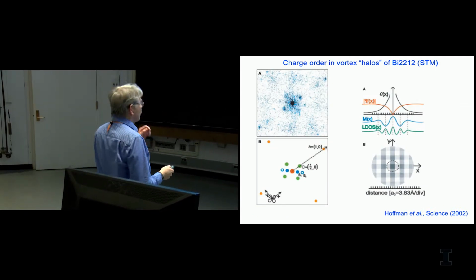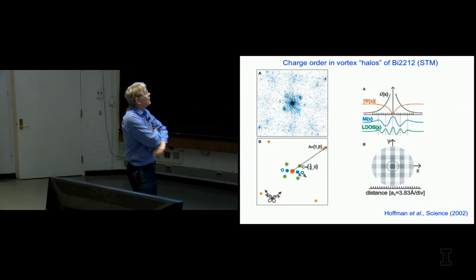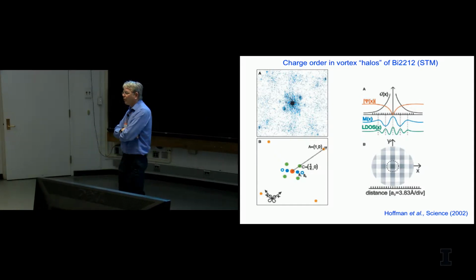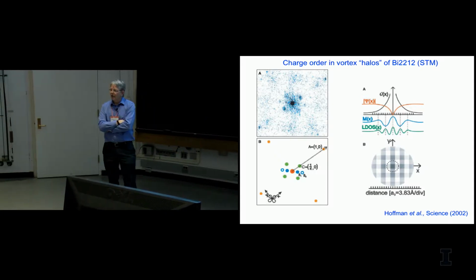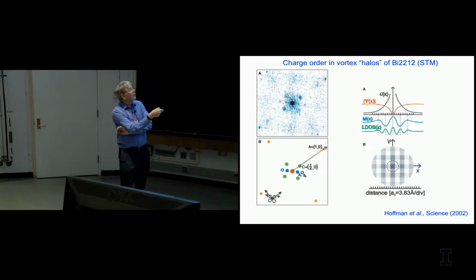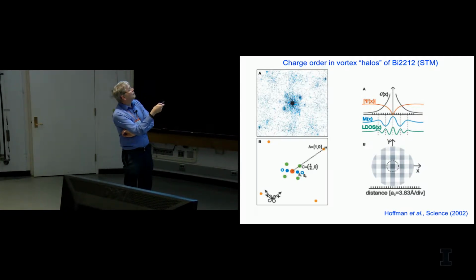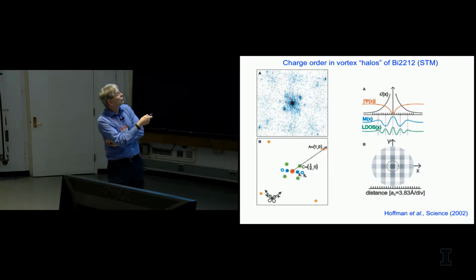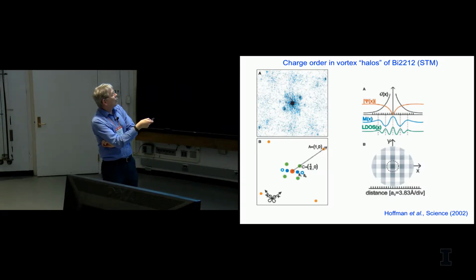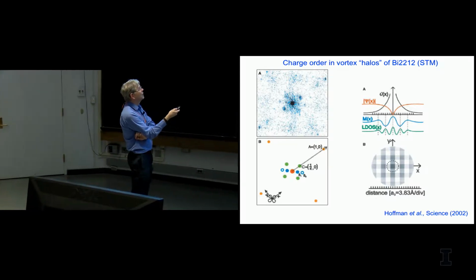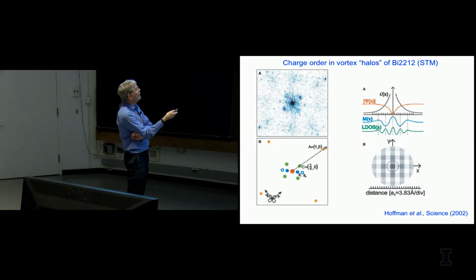So one of the more dramatic things was that charge order of some sort people suspected was playing a role in the phase diagram. Eduardo and his colleagues like Steve were earlier proponents of this. This really came to the forefront when STM developed to an extent where they could actually start seeing some very interesting effects. And this is an early experiment done by Jenny Hoffman when she was in Seamus Davis's group. And they looked at the halo around vortex core. So the vortex core itself is very small because these are small coherence-length superconductors. But outside of this, they saw a halo that indicated some kind of checkerboard-type charge ordering occur.